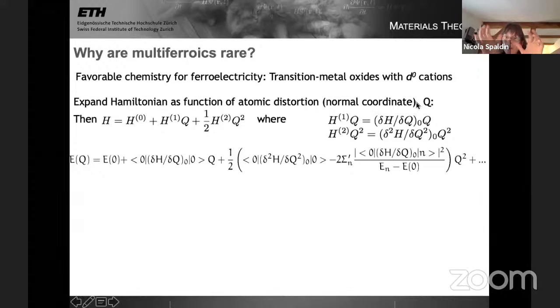In barium titanate, it's really a combination of titanium and oxygen and barium. It's the normal mode that takes you from the paraelectric to the ferroelectric structure. And so one does a normal perturbation theory expansion in this coordinate describing the ferroelectric distortion. H1, of course, is the first order correction, which is just dH by dQ times Q. And H2 is the second order correction, which is d2H by dQ squared times Q squared. Well, sorry, H2 is just the d2H by dQ squared part.